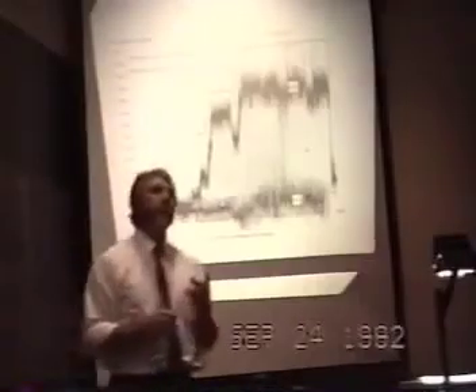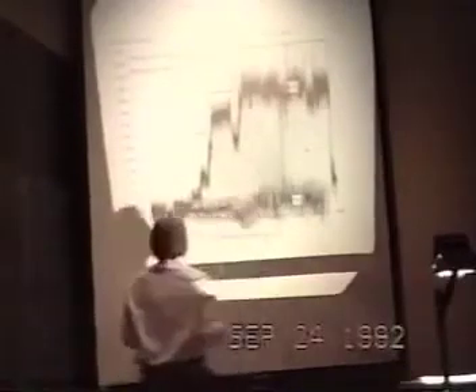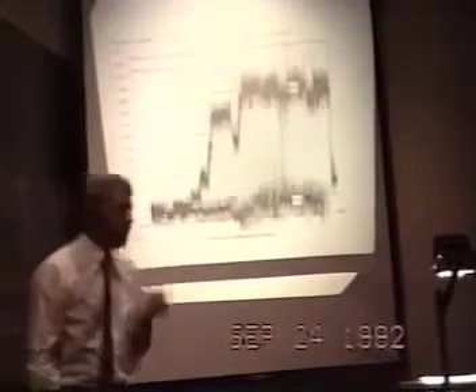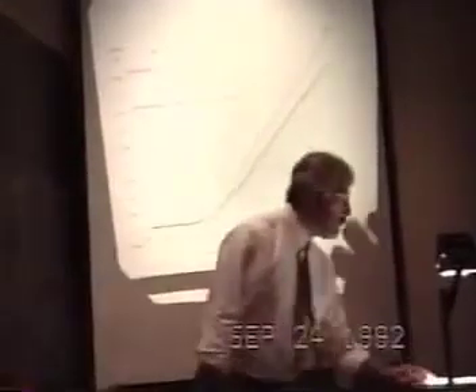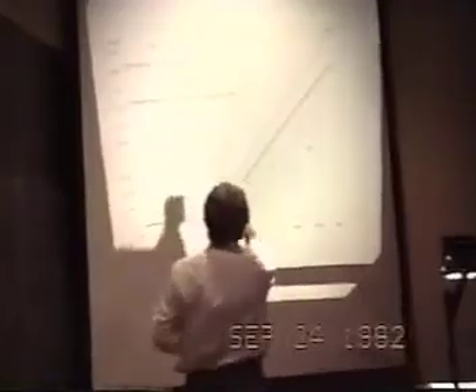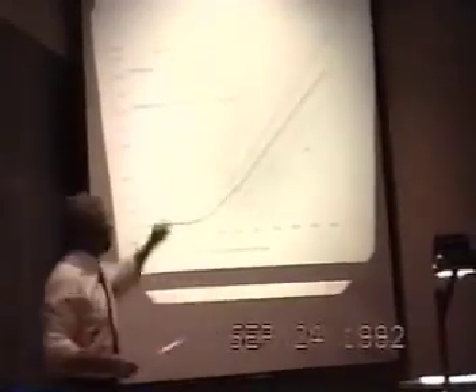And the calorimeter at the same time, electrically in series and powered from the same current source, was P14. And for the same period of time, we observe this form of excess power, 0.21 megajoules, plus or minus its assigned uncertainty, at a time in response to the current ramp shown. So here we have a case where the calorimeter was under identical conditions. The two experiments were side by side and the calorimeter being measured with the same measurement devices, and we observe excess power in a heavy water cell, but we did not observe it with the light water cell. This is a rather small observation of excess power. The energy under this, as I said before, is of the order of 0.2 megajoules with its assigned uncertainty of the amount denoted.